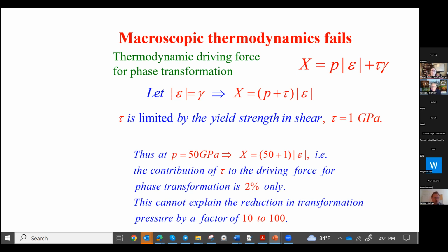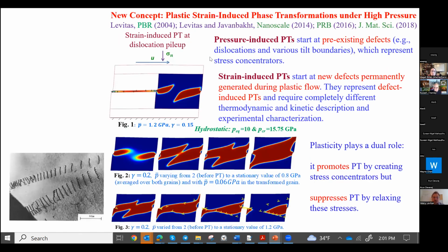Okay. Two points. First, if we are talking about nucleation, no chances. The key point is that we apply relatively low pressure, and the macroscopic yield strength in shear is, let's say, 1 GPa, 2 GPa, right? But stress localization here could be huge, proportional to the number of dislocations. For example, you see here that the average pressure we apply is just 1.2 GPa, but it's already a phase transition, which requires 16 GPa. Yeah, that's fine. And this is because of a local stress concentrator.